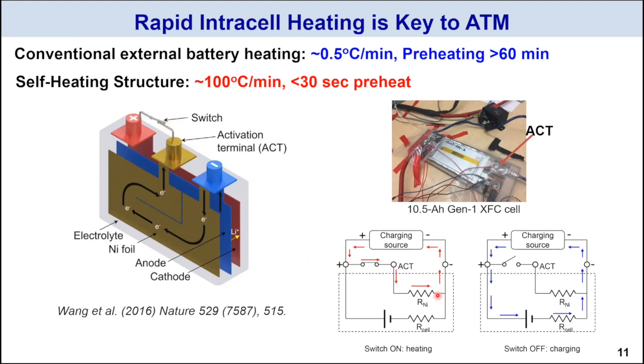And you take such a battery to a charger and connect it as usual. So positive, negative. Now, before you do the charging, you turn on the switch, and therefore the charge current will all flow through the nickel foil to preheat the cell from whatever ambient temperature to 60, let's say. And after the charge temperature is reached, you turn off the switch, and then the same charge current starts to charge the battery material. So it's only one key action, and you will be able to accomplish this process very quickly.